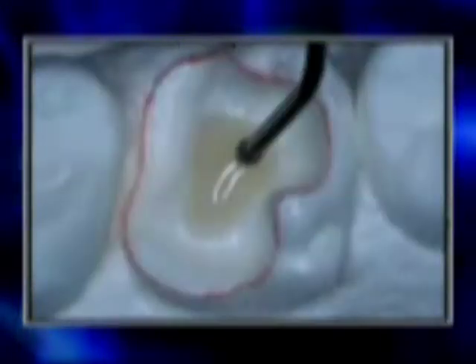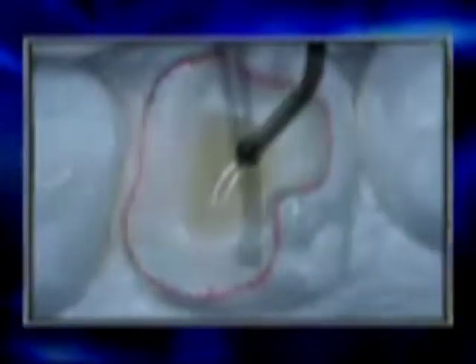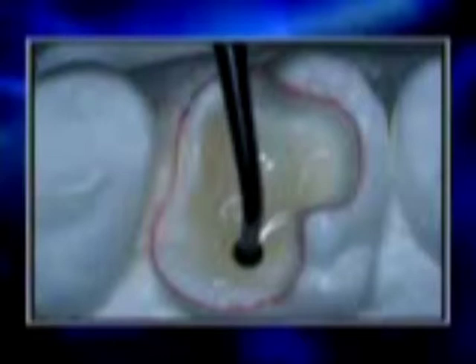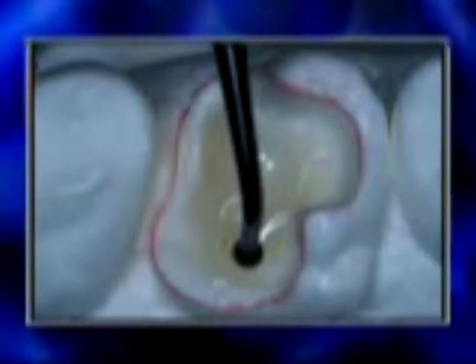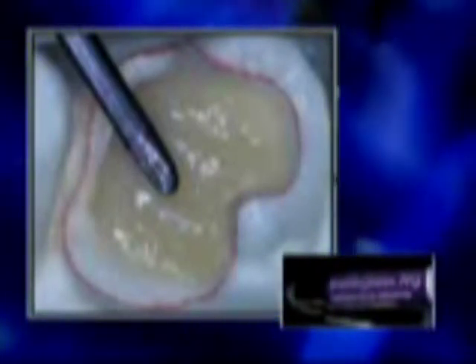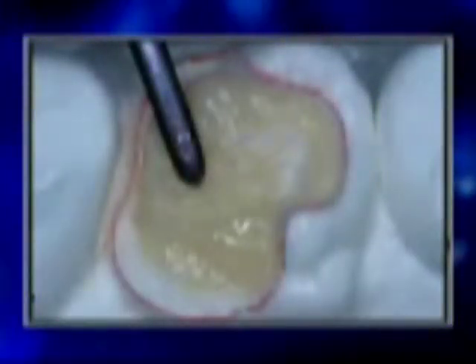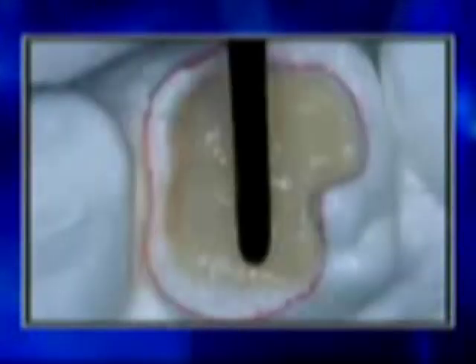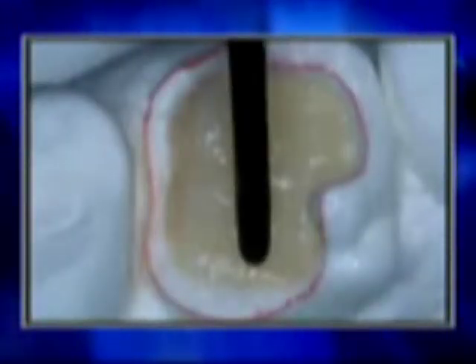A thin layer, 0.5mm, of an A2 shaded flowable composite is injected and uniformly distributed with a ball-tipped instrument using an M1 by Ultradent, and then it is light-cured. This thin layer provides optimal internal adaptation to the pulpal floor of the preparation. An A2 shaded opaque dentin using BelleGlass NG is placed as an artificial dentin layer. The pre-measured reinforcement fiber is incorporated into the uncured dentin layer and light-cured. The selection of an opaque dentin allows the fibers to be completely disguised, and the initial thin composite layer prevents the fibers that are subsequently incorporated from being exposed during surface treatment, which could cause tissue irritation, water absorption, change in color, and the potential delamination of the material.